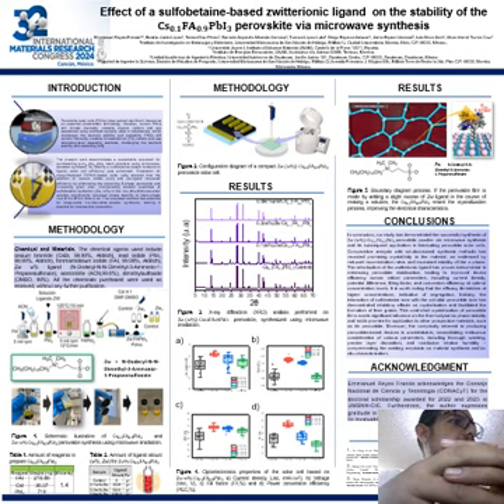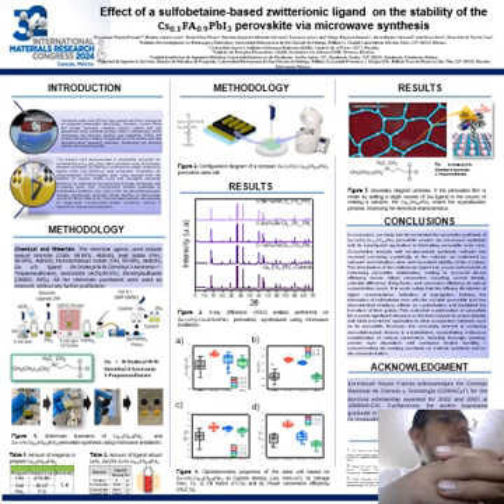Regarding the methodology, the chemicals and materials that we use include cesium bromide, lead iodide, formamidinium iodide, and obviously in this case the zwitterionic ligand, which is N-dodecyl-N,N-dimethyl-3-ammonio-1-propane sulfonate, plus acetonitrile, DMSO, and DMF, dimethyl sulfoxide and dimethylformamide. The chemicals were used as received, without any further purification. As we can see in figure number 1, it implies the preparation of the precursors into the vials.